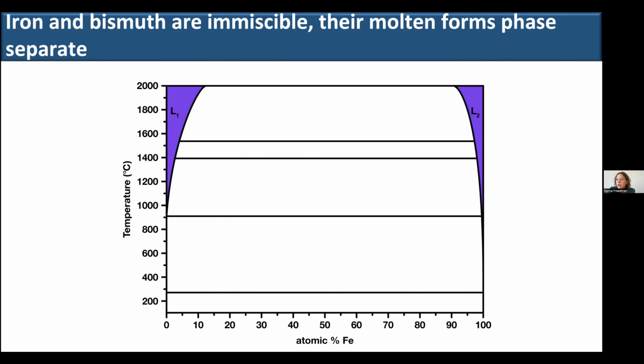So if we look at the iron bismuth phase diagram, and here we've moved back to composition versus temperature, what we can see is that iron and bismuth barely mix with each other. They're more like oil and water rather than water and ethanol. So we have our phase segregated compound, and what this told us is that we would likely have to try slightly higher pressures.